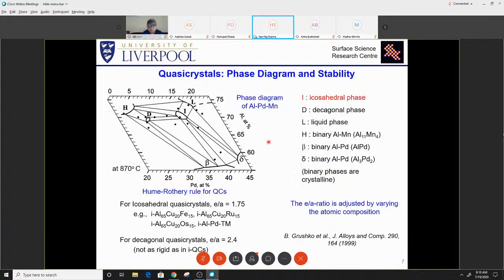The quasicrystalline phases are stable in a very narrow composition range. For example, for the common aluminum, palladium, manganese quasicrystal, it is stable only around this region. That means it should have around 70% aluminum and 15% palladium and manganese each. Well, this is because the ratio between valence electrons and atoms should be specific for the specific class. So if you're working on alloy materials, in order to fulfill this criterion, the composition has to be very specific. Move slightly away from this region, and you move from the quasicrystalline region to other periodic phases.